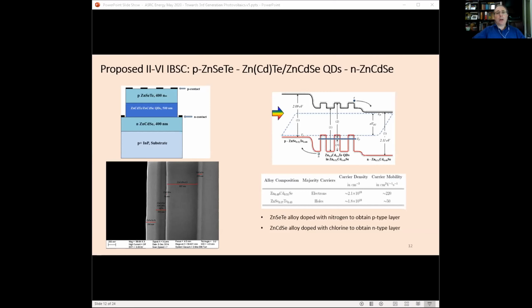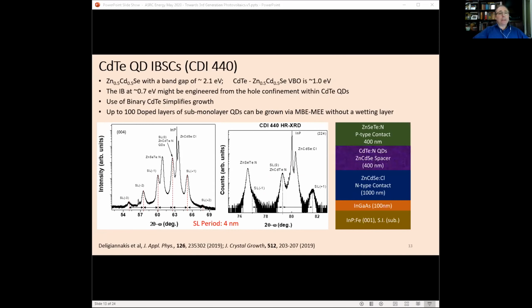And the important part here is that the active layer was made out of ternary quantum dots. And we spent a lot of time working on the details of how to avoid that. So I'll show you only very recent results where we actually changed this approach from ternary quantum dots to binary quantum dots. Now we grow our material using binary quantum dots, in this case, cadmium telluride. And again, for the experts, you can see this is X-ray diffraction in symmetric and so-called asymmetric configuration. And because of the observation of multiple superlattice peaks, you see the quality of the devices is high.